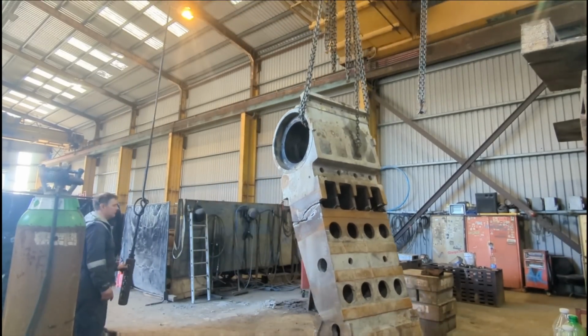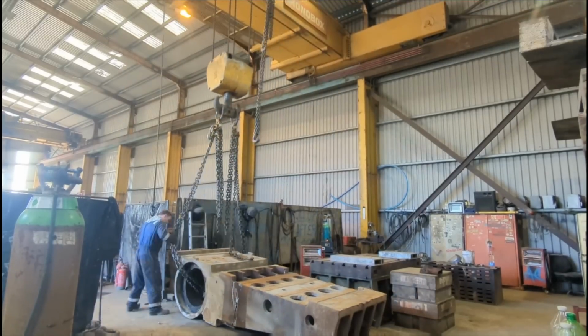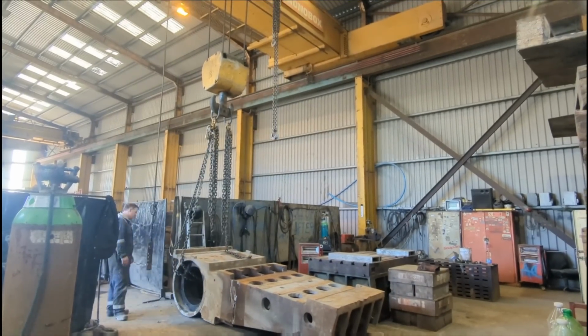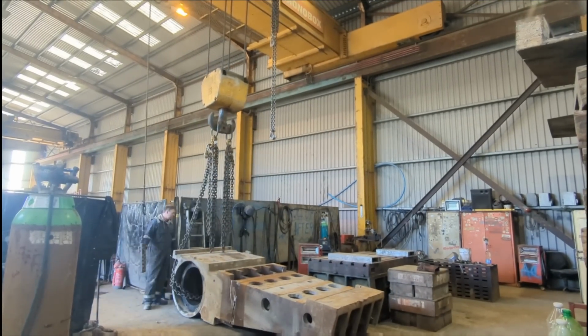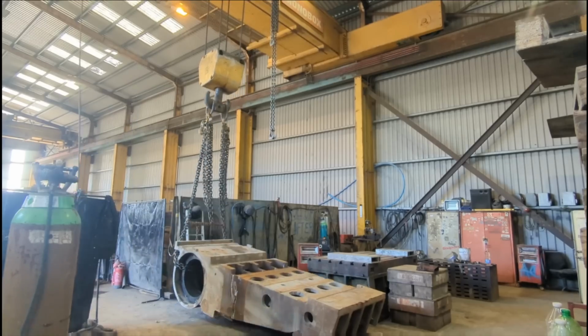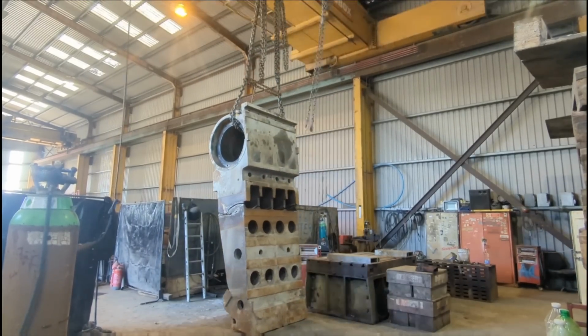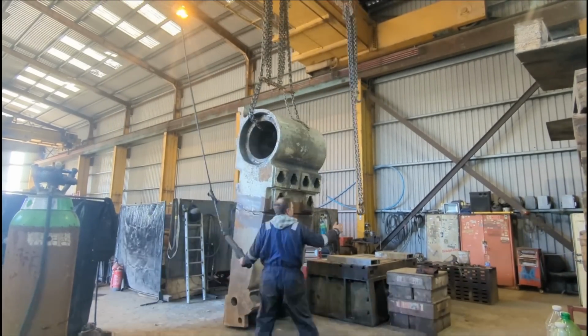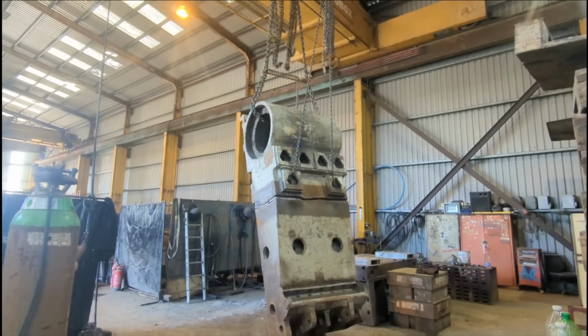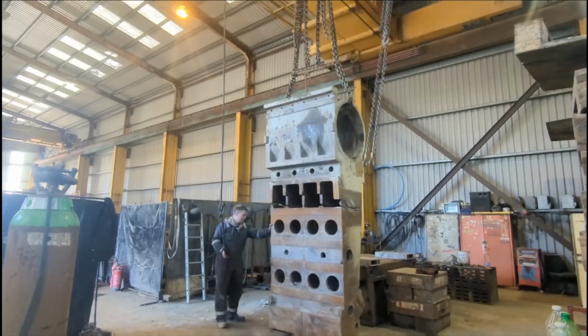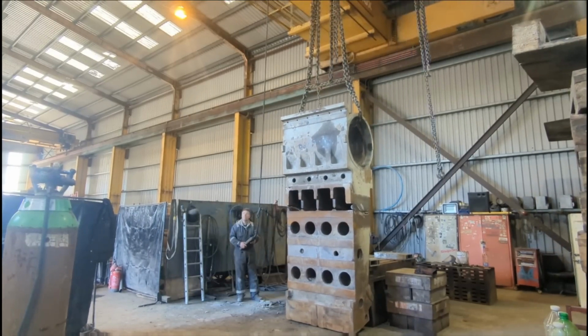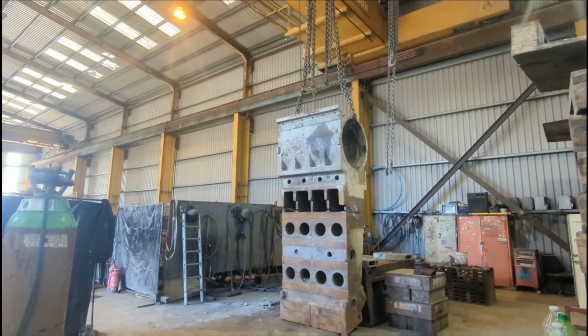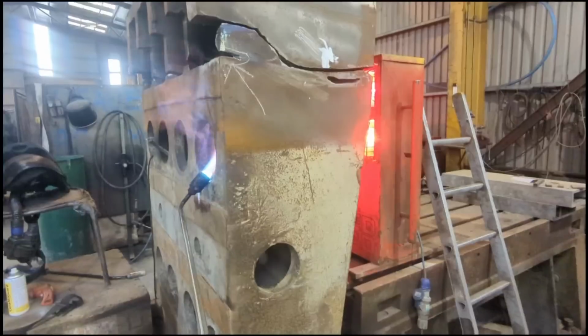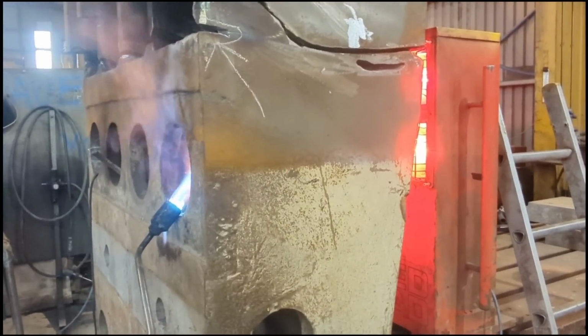At this point it's hard to convey how happy I am that my welds didn't break with that impromptu weld test. The chains I'm using to lift are rated far in excess of the weight that I'm lifting, so there's no issue to them. The tack welds have survived that shock loading. This is a good indicator that the welding wire is a good metal match to the base material. So finally we'll get some preheat into this monster.